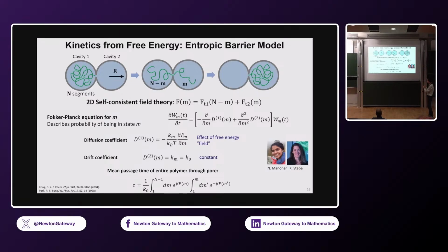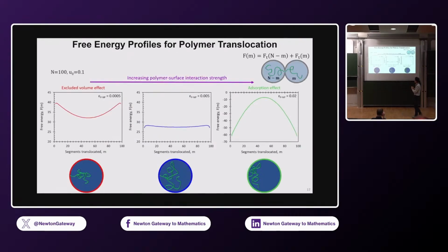It will do that by snaking this end and then translating some subunits of this polymer into the second cavity, right? What we can do is we can calculate the free energy of different states using self-consistent mean field theory, okay? And then use this Fokker-Planck formalism to go from free energy, which will give you a probability of each state, to basically learn and understand how the kinetics would change as you change the interaction strengths between the polymer and the surface of that cavity. Okay, so that's what we did. And here's the free energy profile. So again, this is a polymer with n units, and I'm going to put m units in the second cavity. Okay, so when you go from 0 to 100, that's when you have full translocation.